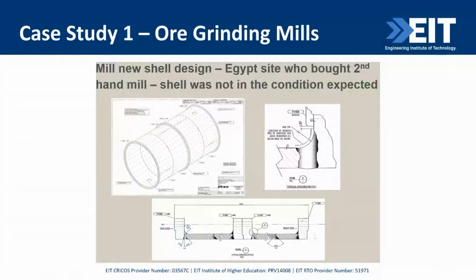This is a new shell we designed for an Egyptian site who bought a second-hand mill, which was not in the condition it should have been when it got delivered. And the weld joint detailing is obvious. So all the shell to flange welds are full penetration, they're all oversized legs so you can fully grind and profile them to reduce the stress concentration. Very high quality welds, highest quality NDT. You must have an excessive leg, so when you fully profile, you don't have too low a weld throat. Obviously, you'll confirm all this with your solid element FE.